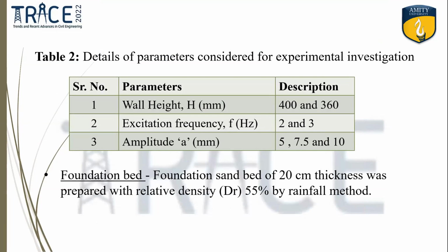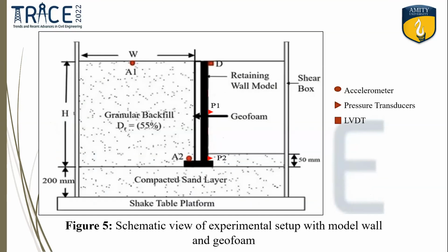Experimental investigation: there are three parameters selected. The wall heights are 400 mm and 360 mm. Two wall heights are selected to determine the effect of height of wall. Frequency was selected, and amplitudes were selected: 5 mm, 7.5 mm, and 10 mm. The thickness of foundation is determined. The backfill is prepared by the sand rainfall method. The density of sand is constant throughout the whole experiment. Figure 5 shows the schematic view of the setup.